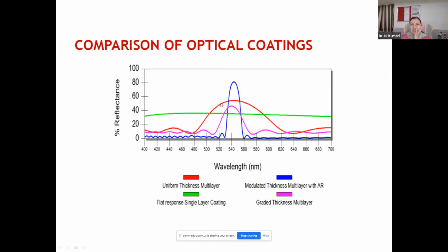And then this red one is the uniform thickness multi-layer. Here the full width at half maximum of the band was quite large. So there also the light intensity was decreasing because it was covering a very broad band. And further, we came for thickness modulated, and finally for